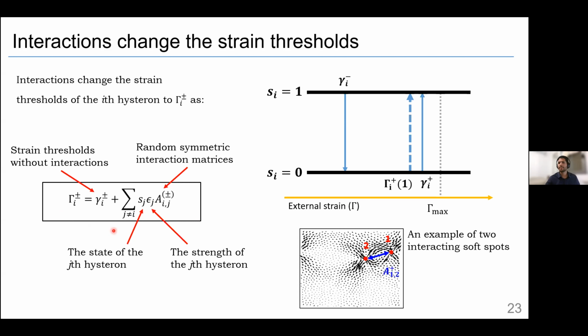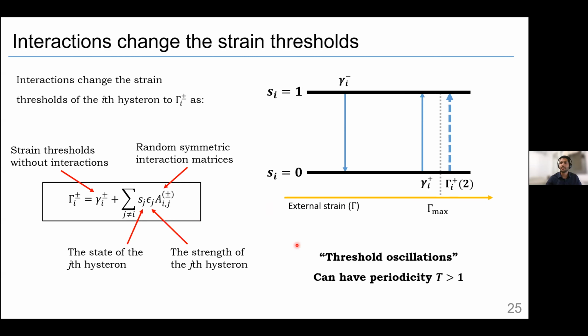What happens is that we can have a different gamma plus for the same hysteron. In this case, gamma plus is still below gamma max, so we can still have the periodicity. But it can also be larger than gamma max. And in this case, this hysteron is not active. And if it moves periodically between the two states, we reach something that we call threshold oscillations. So the hysterons do threshold oscillations, which can have periodicity larger than 1.